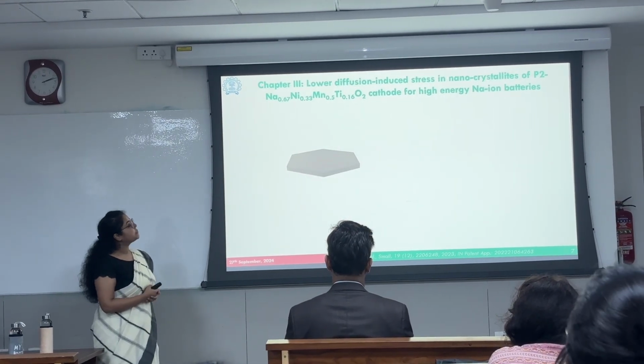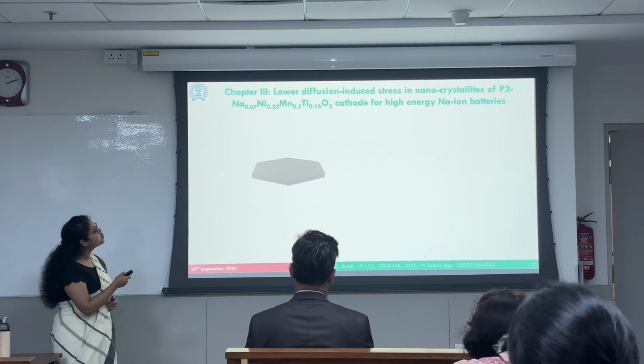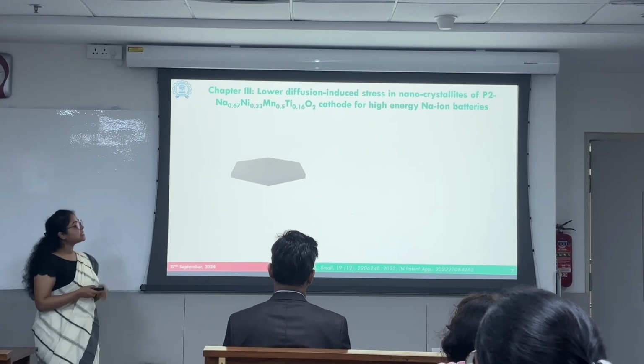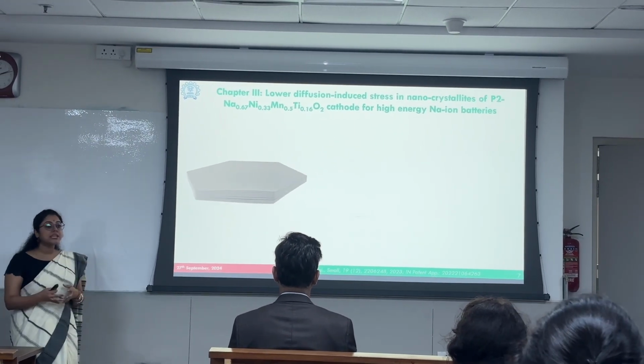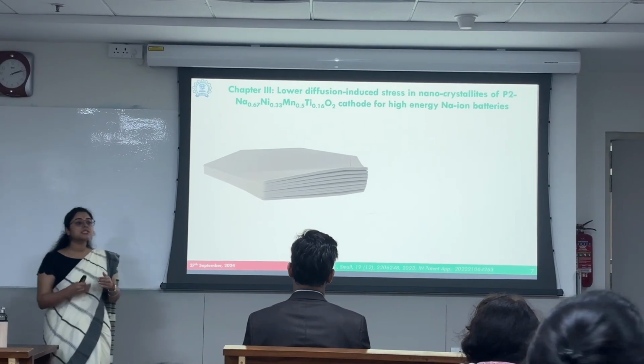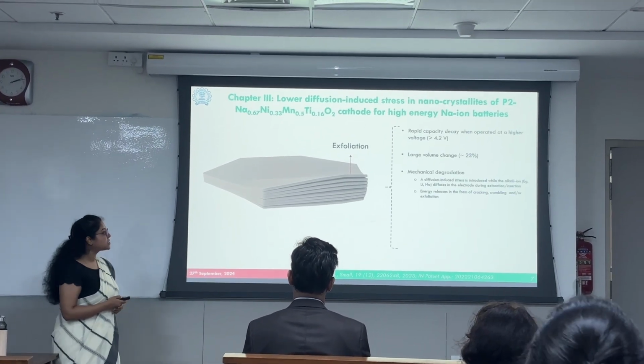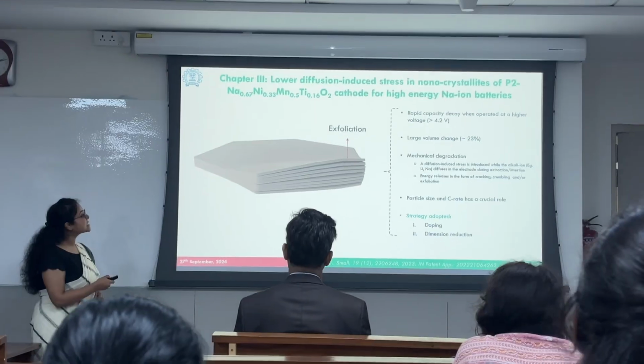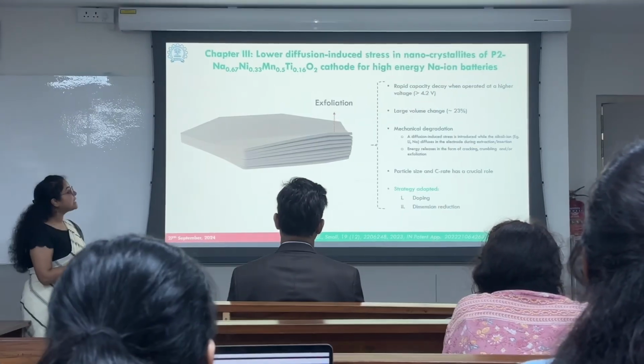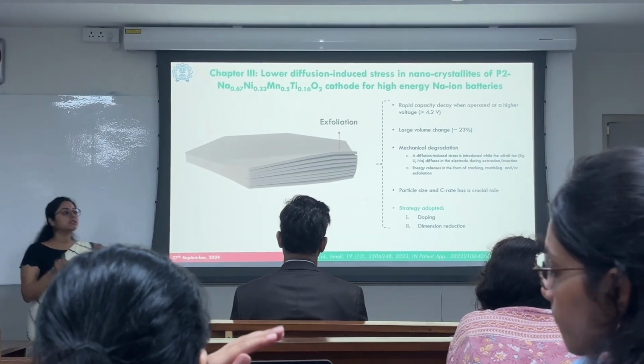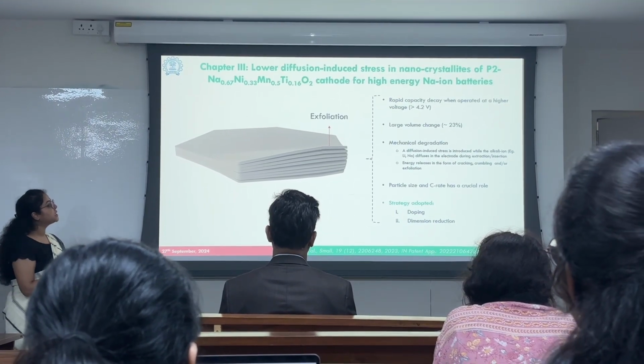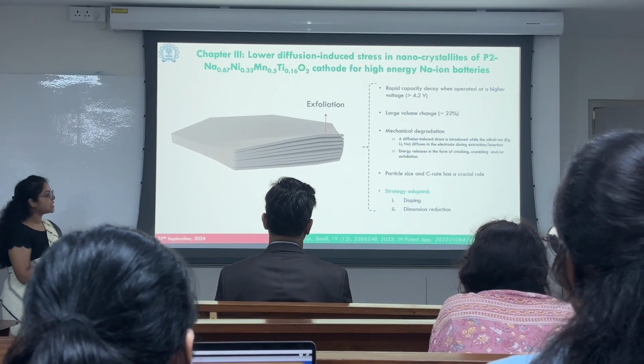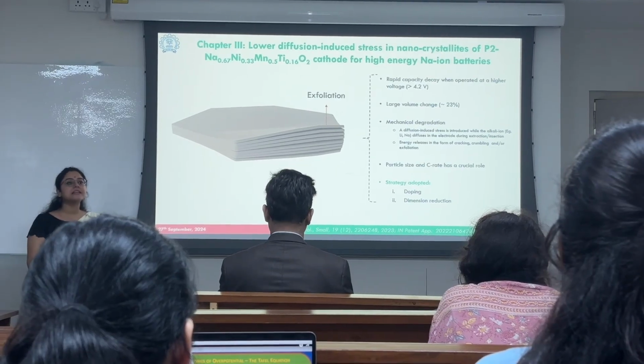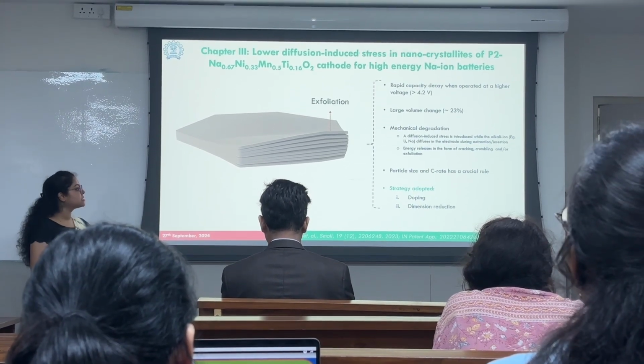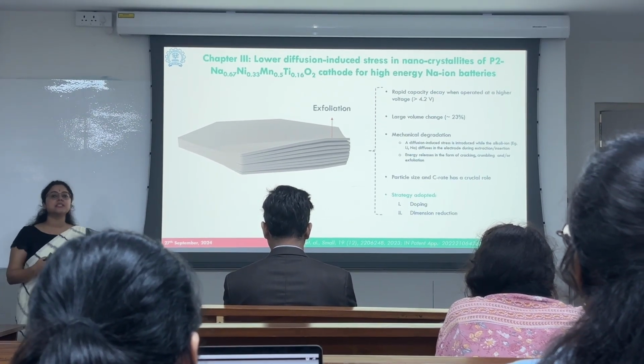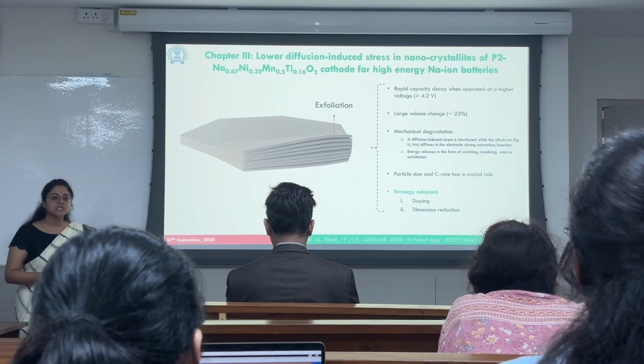So in the first chapter, we dealt with the problem of diffusion-induced stress. We have seen in the consequences that exfoliation is the major problem which comes out of the irreversible P2-O2 phase transition, leading to rapid capacity decay, large volume change, and mechanical degradation. It is to be understood that the major root cause of this degradation is the diffusion-induced stress, which is introduced when the alkali ions diffuse during the extraction and insertion, and then the energy is released in the form of cracking, crumbling, or exfoliation.